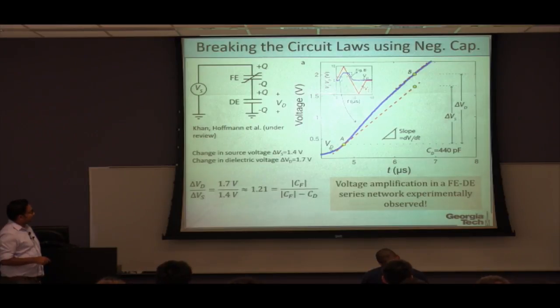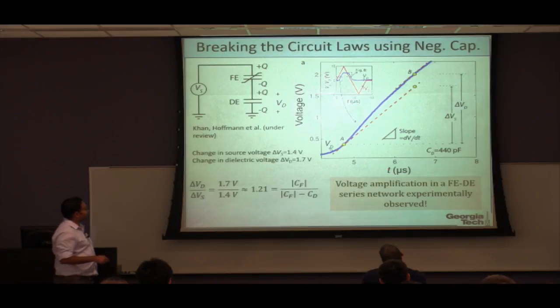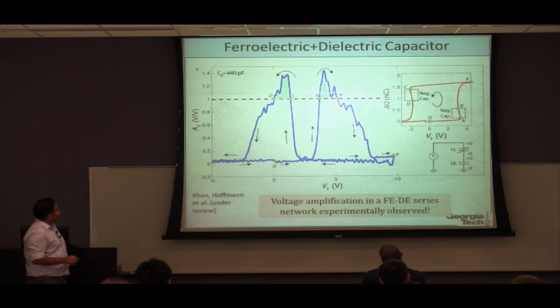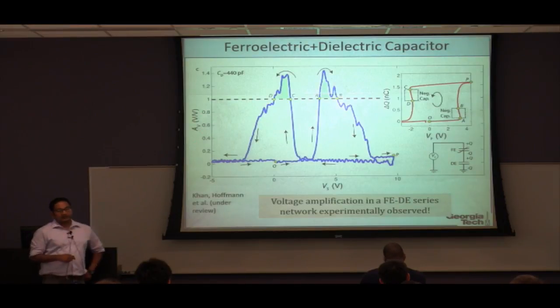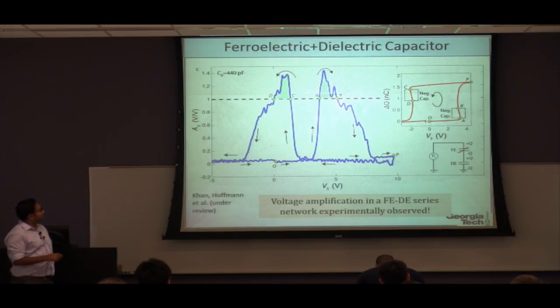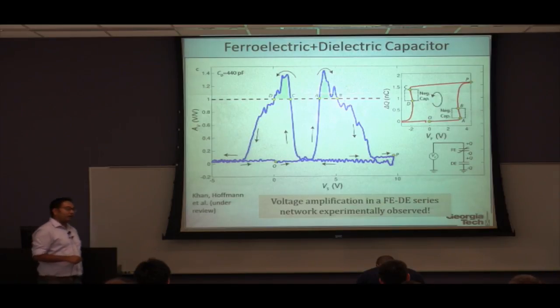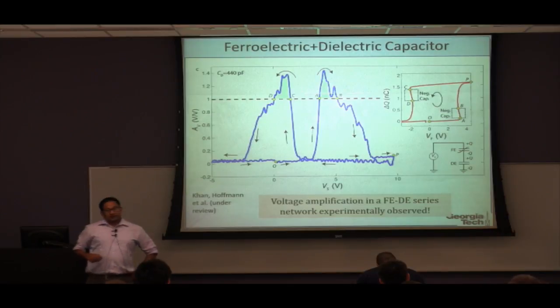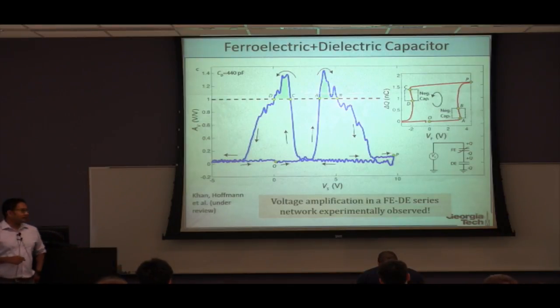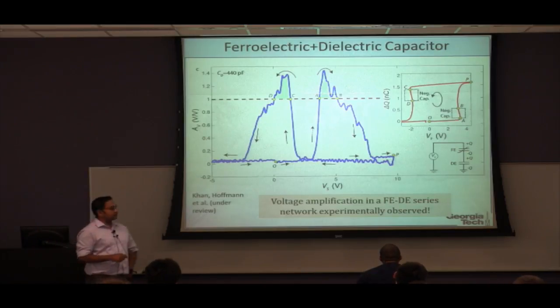And what we can show is that this red curve is the ramp rate of the applied voltage, Vs, and this blue curve is the voltage that we measure across the dielectric. And what we can clearly see is that the slope of change of the dielectric voltage is actually larger than the slope of the applied voltage. And if we plot this ratio dVd over dVs, we can clearly see that there is an amplification in a certain range of voltages that we applied. So again, this shows that you can get voltage amplification in a ferroelectric dielectric series network.